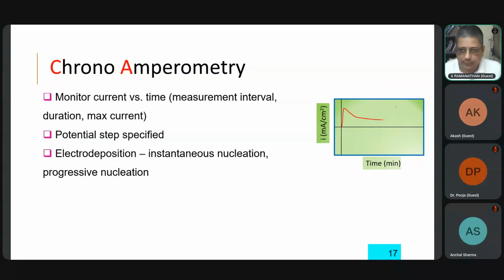You can find that out by monitoring this. If the response current goes very quickly up, comes down and then stabilizes, it's likely to be instantaneous. If the response current goes gradually and then comes down, that is likely to be continuous or progressive nucleation.